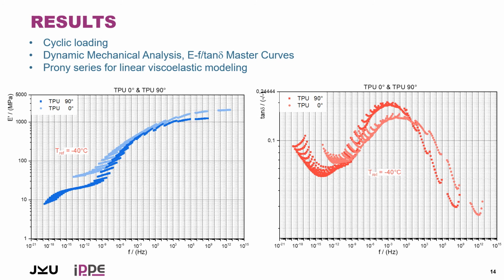If you fit, for example, these master curves using the generalized Maxwell model, you may determine the parameters of a Prony series, which is the most typical linear viscoelastic model for viscoelastic deformation analysis. This is also available. Does it mean we have characterized the orientation dependent, anisotropic, small strain deformation behavior, viscoelasticity, for these materials.